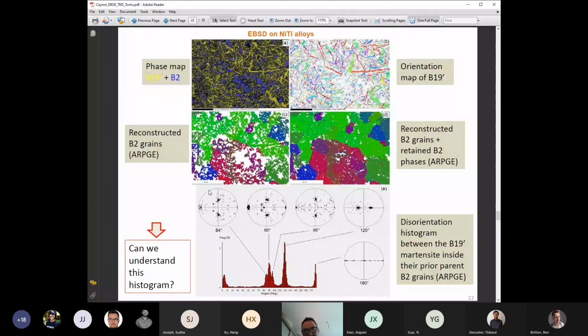In the second line, you have two images. I will skip them. It's just to tell you that I was able to reconstruct the full B2 grains, also by using the same software, but it's not of interest here. What is of interest is that at the bottom, you see these misorientation histograms. So you see that it's not random. You can call them twins. Well, it's actually variants, but you can call them twins. And in addition to the misorientation angle, you can also plot the misorientation axis corresponding to the misorientation angles. And you see that they are very specific. They are not randomly oriented. They are not distributed everywhere in the pole figures. So my question is, can we understand this histogram of misorientation?